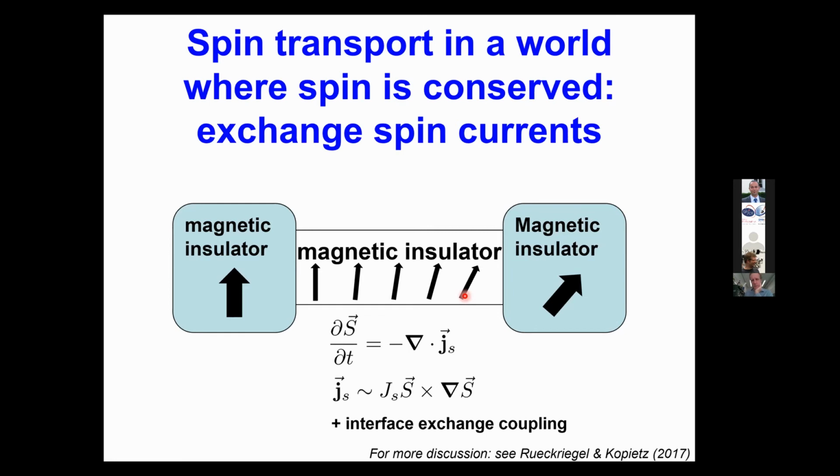So I think once again, for a ferromagnet, even for an easy plane ferromagnet, probably it wouldn't work because the magnon spectrum is quadratic, and that violates the Landau criterion of superfluidity. No, in an easy plane ferromagnet, if the magnon spectrum is linear, then at least there is no problem with the Landau criterion. Maybe there are some other problems.